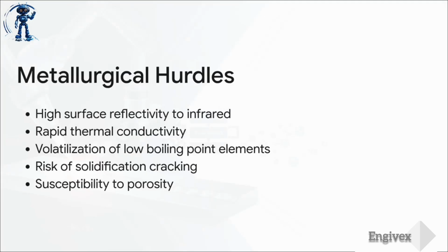Well, here's the harsh reality of what happens when you blast aluminum with intense energy. First off, it has insanely high surface reflectivity to infrared light. It literally just bounces the laser energy right back in your face. Second, it has extremely rapid thermal conductivity. Basically, it acts like a giant heat sink, aggressively pulling the heat away from your weld zone way faster than you can pump it in.